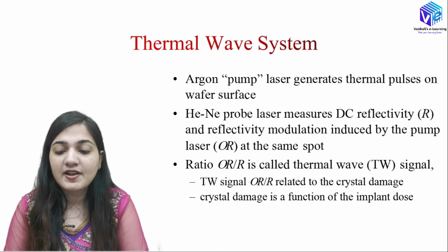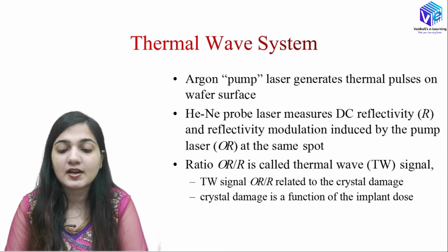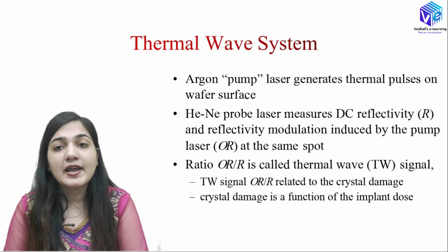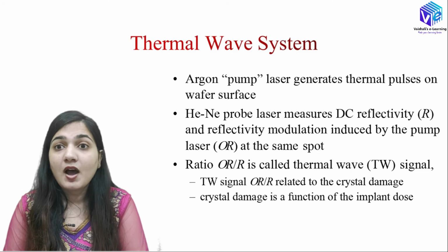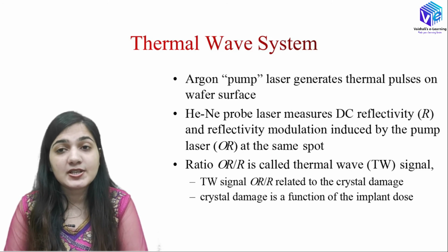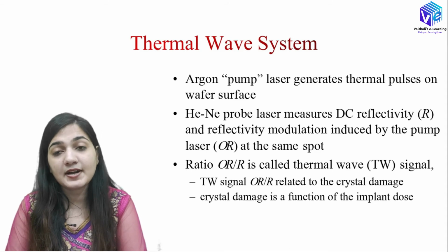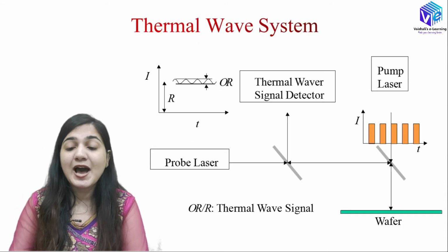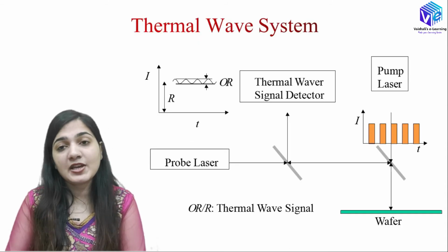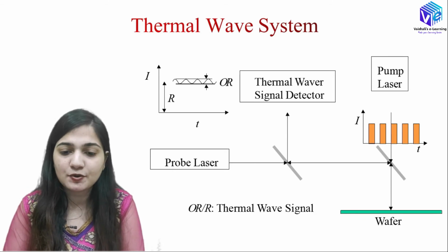The thermal wave signal, ΔR to R, is related to the crystal damage. If I know the thermal wave signal, I will know the amount of crystal damage inside my wafer. Crystal damage is a function of the implantation dose. So this is how indirectly I am measuring the ion implantation dose.